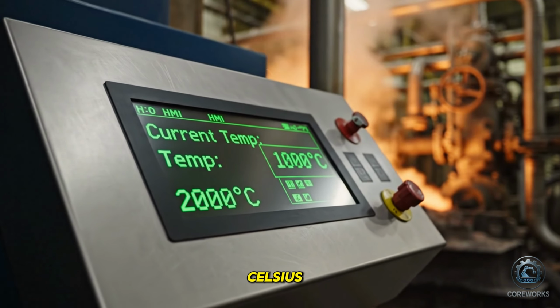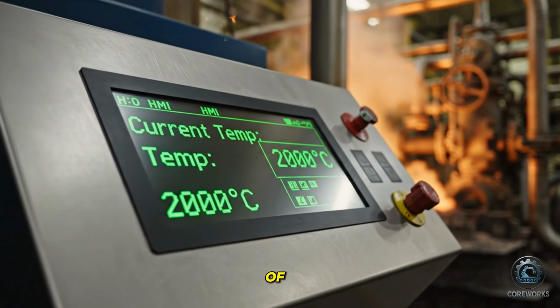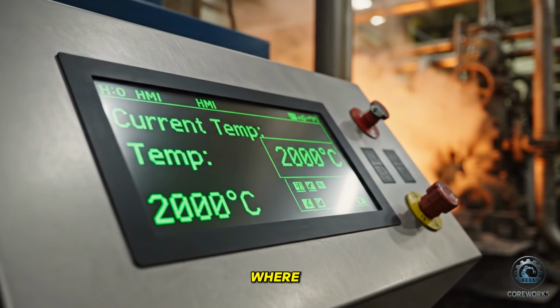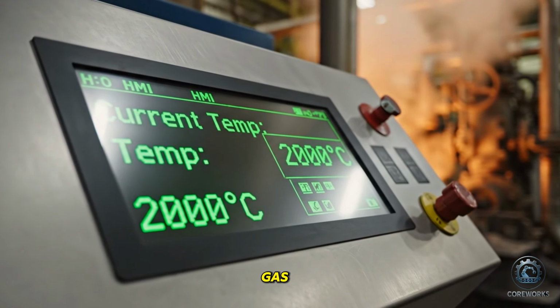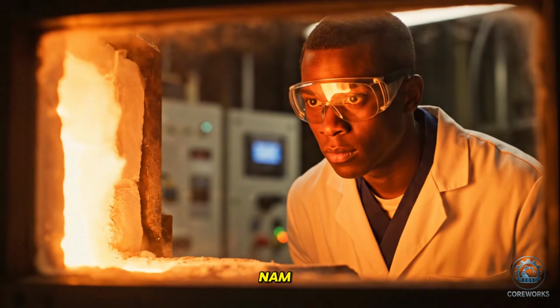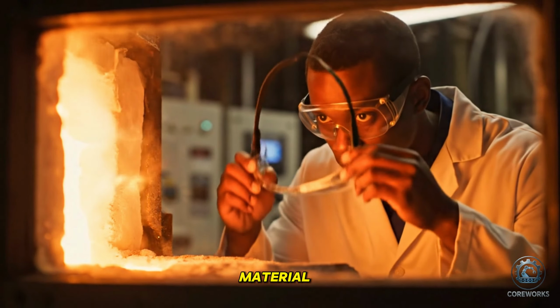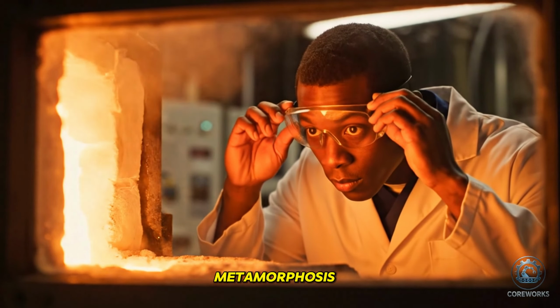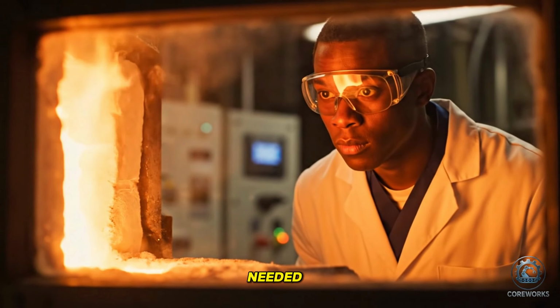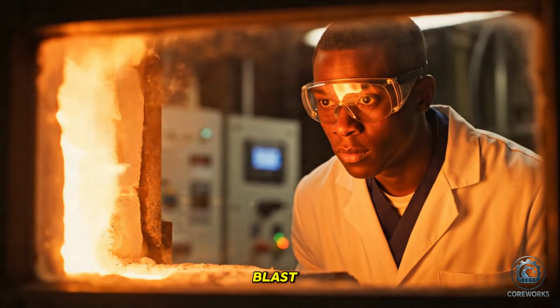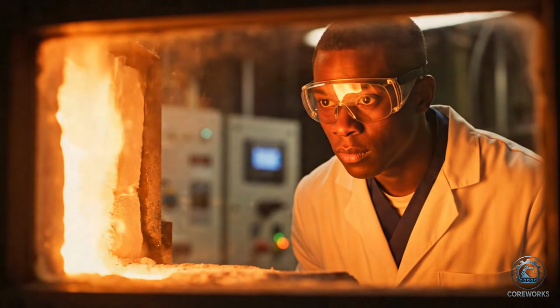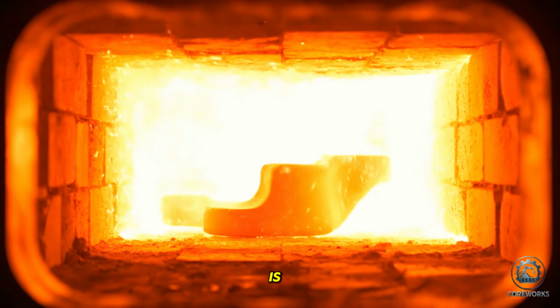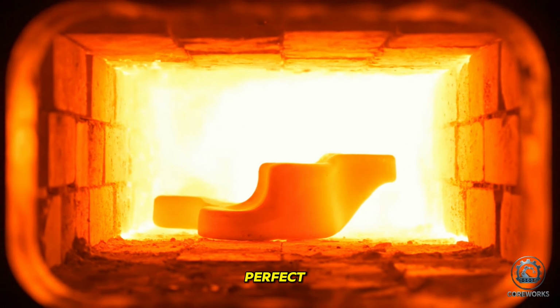2000 degrees Celsius. This is hotter than the surface of some stars, a temperature where most metals would have turned into liquid or gas. Dr. Nam knows that at this temperature, the material is undergoing a total metamorphosis, gaining the properties needed to survive a rocket's engine blast. The part is now white hot. It must hold this temperature for 12 hours to ensure that the crystallization is complete and the density is perfect.